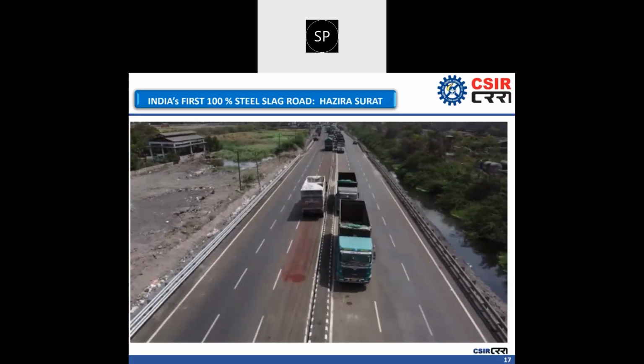For the port, and due to that this road had developed big potholes, and even several layers had completely worn off. Therefore we took this challenge and designed this entire road using slag aggregate, and now for 1.5 years this road is completely intact despite being subjected to very heavy commercial traffic.